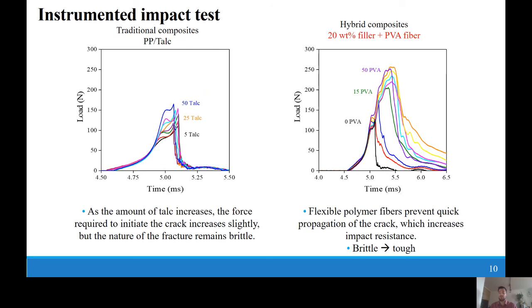Instrumented impact test was also performed on the composites prepared. In this way, we can determine not only the energy absorbed during the fracture, but also the nature of the fracture. The figure on the left shows the force time curves of two-component composites containing different amounts of talc. As the amount of talc increases, the force required to initiate cracking also increases. The area under the curve is related to the amount of energy absorbed during the failure.